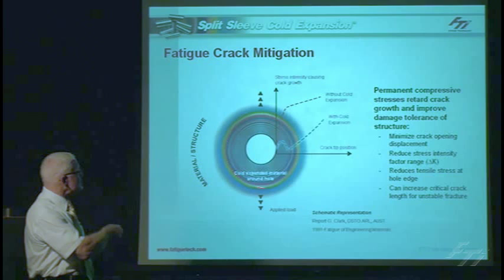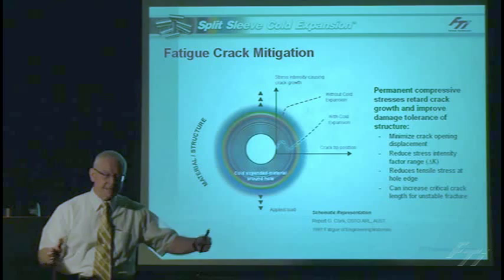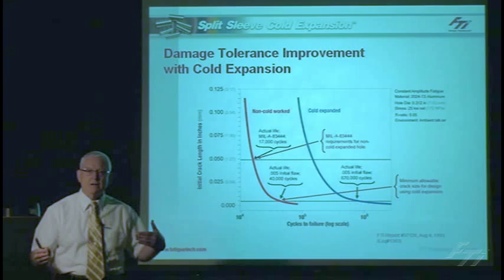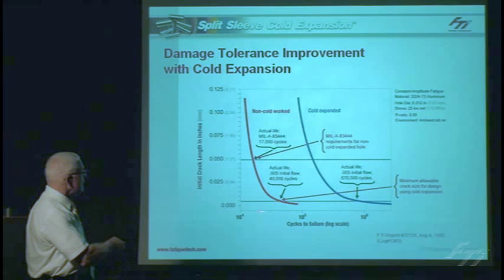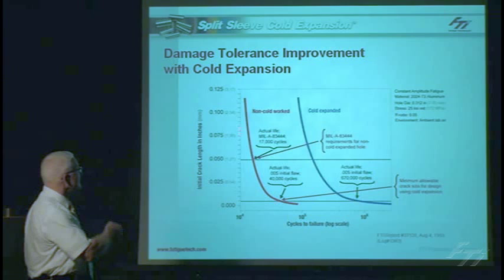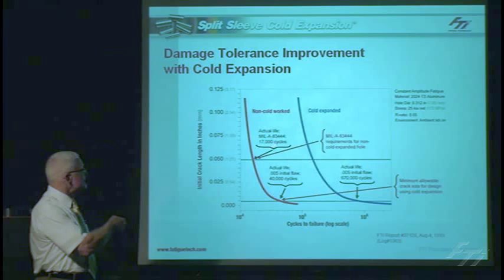The combination of the residual compressive stress will lower the stress intensity factor and slow down the rate of crack propagation through that residual compressive stress zone, meaning we greatly extend the fatigue life. When you look at the US military requirement for damage tolerance, where you assume there's a 50 thousandths flaw, we plot out the crack growth from different initial crack sizes versus the number of cycles for that crack to grow to a critical crack length. Typically assuming a 50 thousandths flaw, this coupon would have only had a life of about 17 thousand cycles.